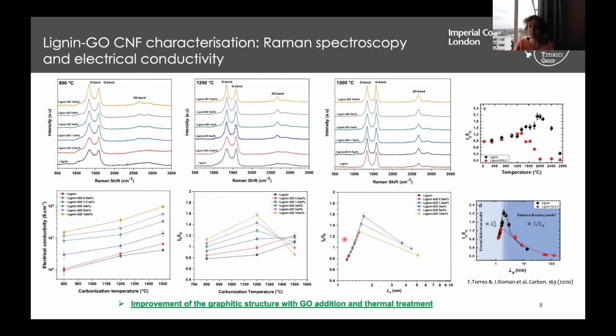What this is telling us is that by adding the graphene oxide, in the cases that we start with this very disordered material, graphene oxide is helping to promote the crystallization of these more ordered domains until a point where they start growing. We can see this by calculating the crystalline size of our domains through Raman by the Ferrari model, and we see how the ID to G ratio increases until a point where the defects really start being reduced, and then the domains start growing.